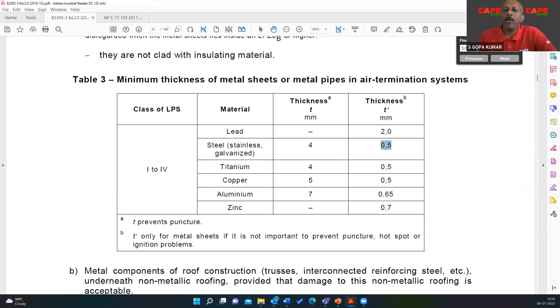Now, aluminium sheet on main head house 0.7 mm thick. So 0.7 mm aluminium, the limit is 0.65. If it is more than 0.65, of course 0.7 means lightning may puncture the aluminium sheet. You have to decide whether you can live with this puncture, or with the hot spots and arcings due to this puncture. If you cannot live with that, you have to put an air termination at the top of the roof. Preferably, you install an air termination mesh and connect it to the sheet itself. That is the best method. I hope it's clear.